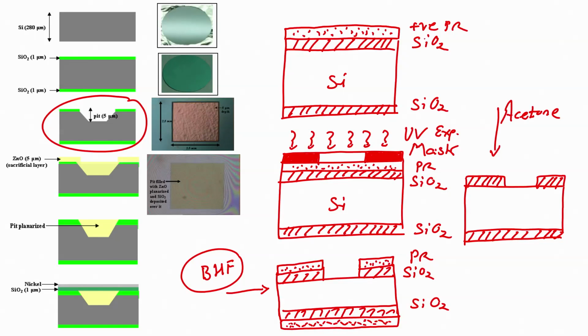So, you see here we have soft bake, then we have exposed, we have developed. After developing, we can spin coat photoresist on the back side and then hard bake, followed by removing the silicon dioxide through BHF, followed by stripping off the photoresist. Here we are with stripping of the photoresist. After that, if you dip this wafer in KOH or TMAH, you etch silicon, and we know the etching rate of KOH and TMAH.